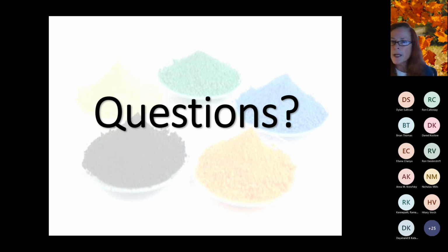The first one is, are any of these mixed metal oxides more readily susceptible to photocatalysis, and how does it affect color stability? So the good thing is these do have a very good weatherability, especially the titanates, where the TiO2 has a large percentage in the formulation. However, it doesn't carry that photodegradation aspect that the TiO2 does.